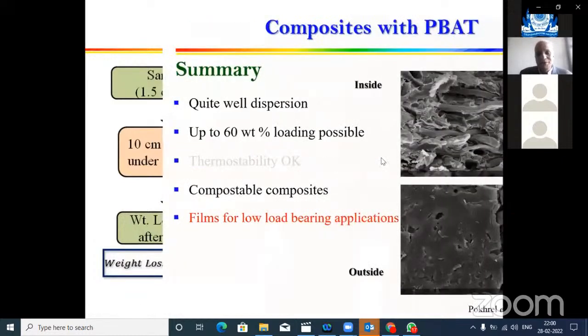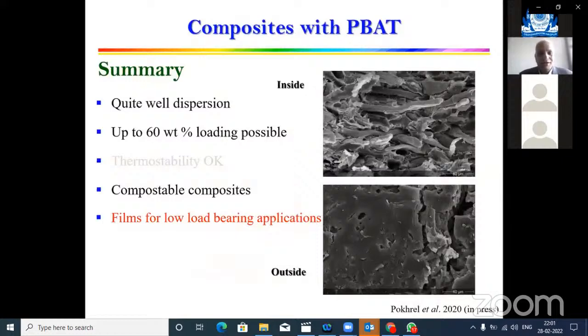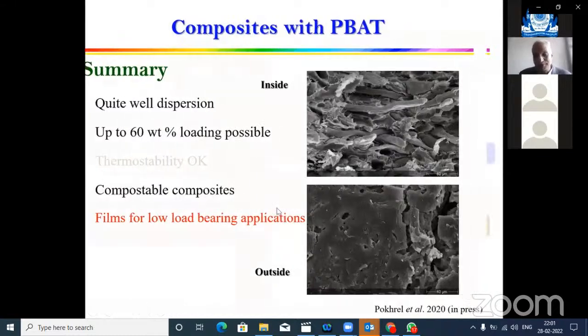So this is quite old work that we did, and to summarize, we found good dispersion of the chitosan in the polymer matrix, with up to 60% by weight of chitosan able to be embedded into the polymer matrix. Thermal stability was also good, and the material was compostable as I showed from the pictures before. However, the films were found to be fit only for low load bearing applications.